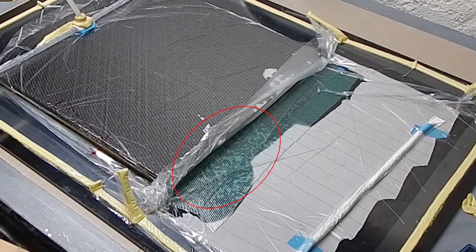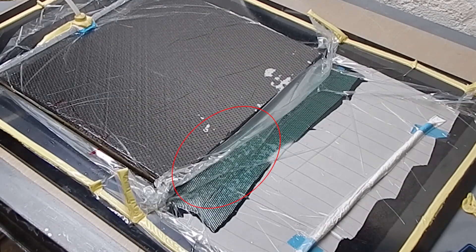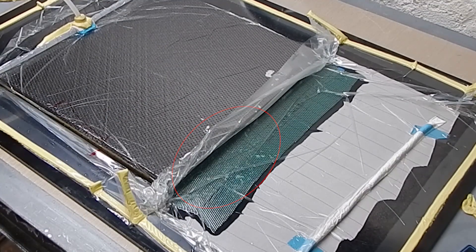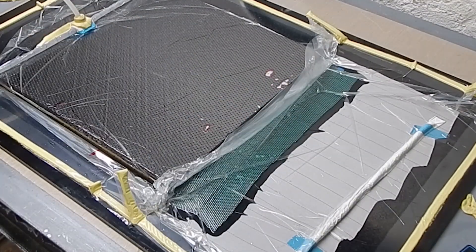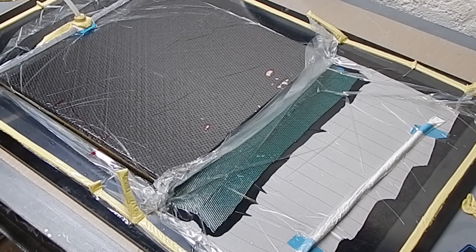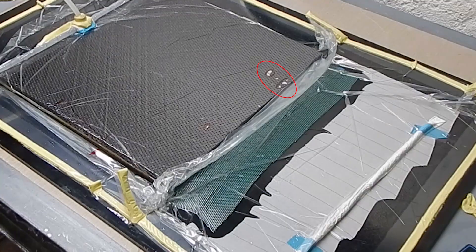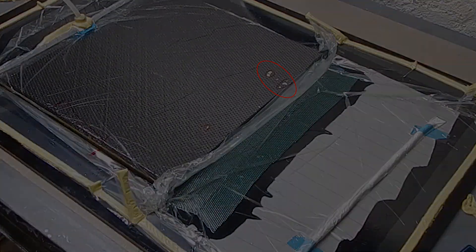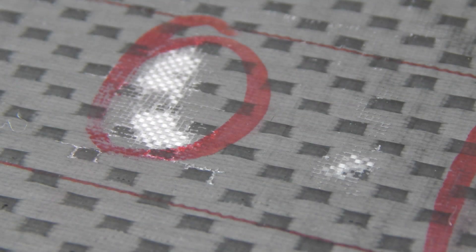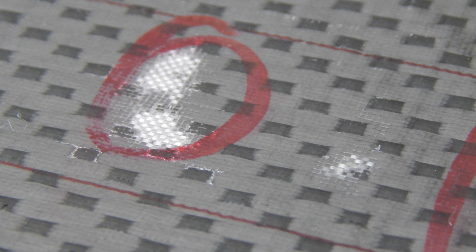And this was a pretty poor way to do this. Ideally I would have lapped that green flow up onto the top skin, or in a perfect world put a taper on the core, or a flange, or some type of tidy way to finish that edge. You can see some air got trapped, stayed trapped, and the panel cured with that air in there.